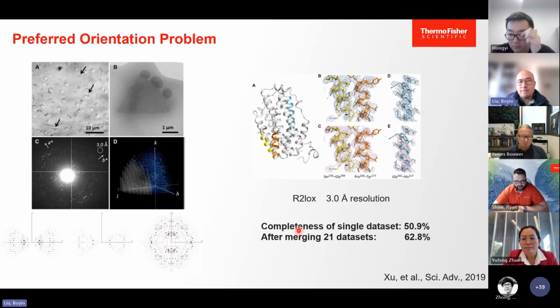They actually achieved 50.9% completeness from one data set, but after merging 21 data sets, the completeness only increased by 12%. So you can see that the preferred orientation is the main obstacle for them in getting a high resolution.